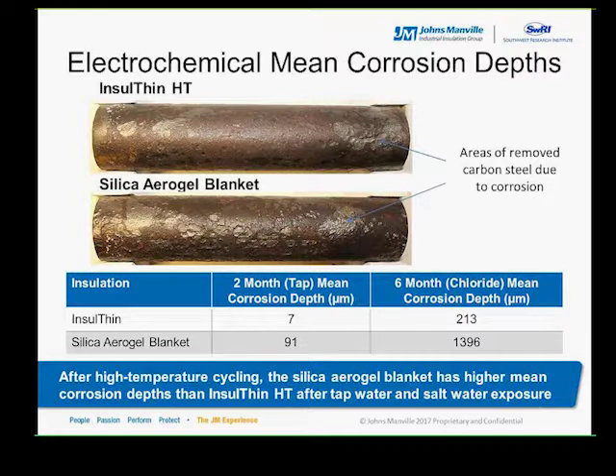So following the same analysis as the cold sweating conditions that I've already shared, shown in this slide are pictures of the samples after a good high pressure wash to remove the corrosion byproducts. The table below again depicts the mean corrosion depth after the 2 months of tap water exposure and then the 6 months of chloride solution exposure. So what we see is, unlike the sweating conditions, you can clearly see in both the pictures and the data in the table that the Insulthin blanket has a much lower corrosion rate than the silica aerogel blanket.